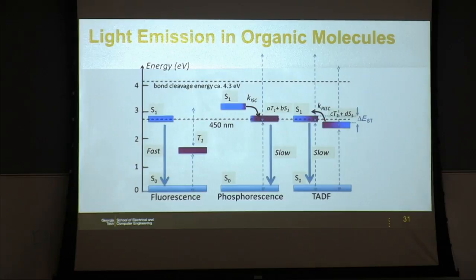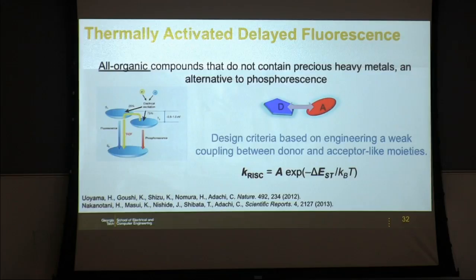So how do you do that? You do that by designing molecules where you have electron donating and electron accepting groups, and by playing with their different coupling and the shape and the overlap of the different HOMO and LUMO orbitals, you can control that energy difference, delta EST. The reverse intersystem crossing is then simply that Boltzmann factor over that barrier of delta EST. So if you make that small enough, you can get very efficient emission from that fluorescent state.